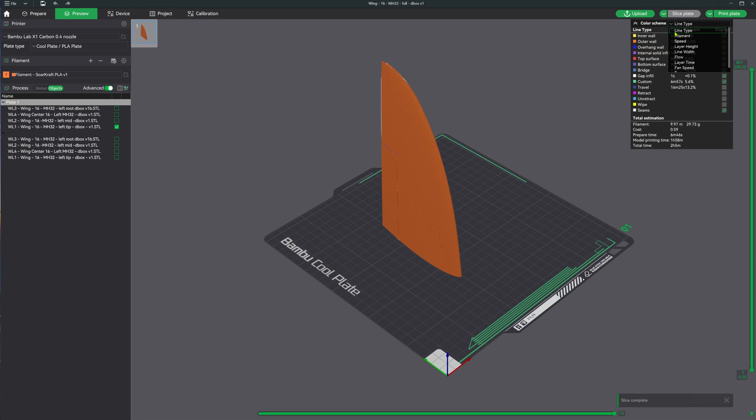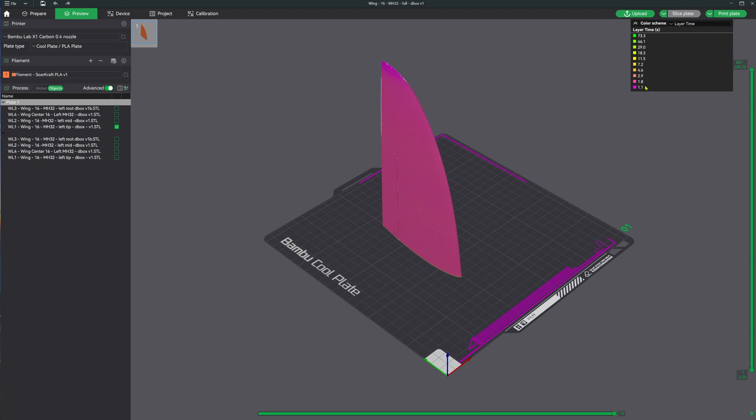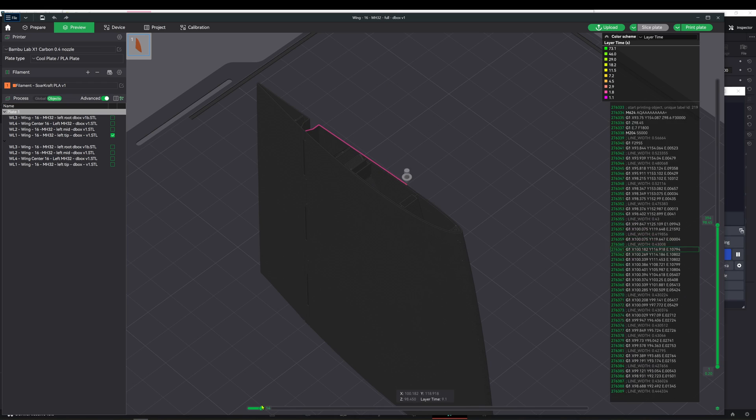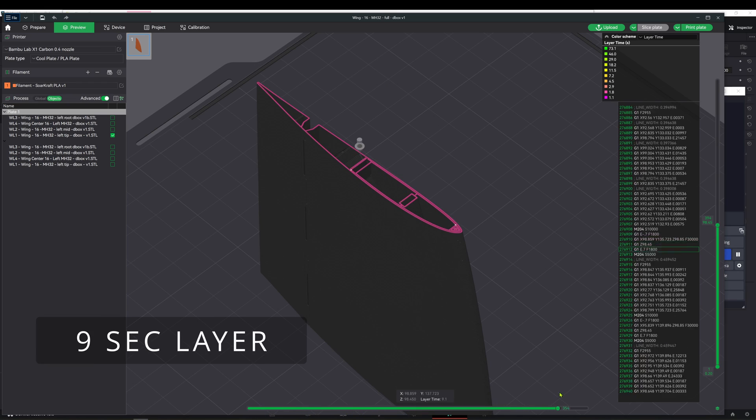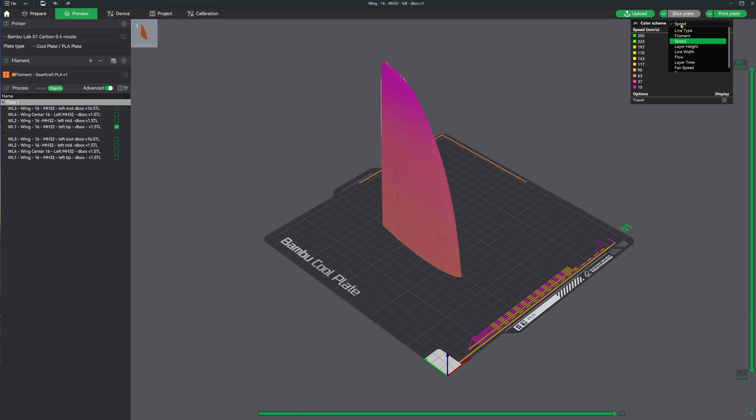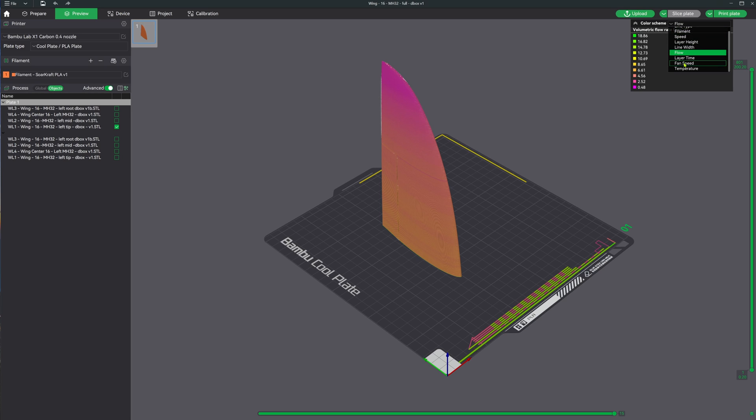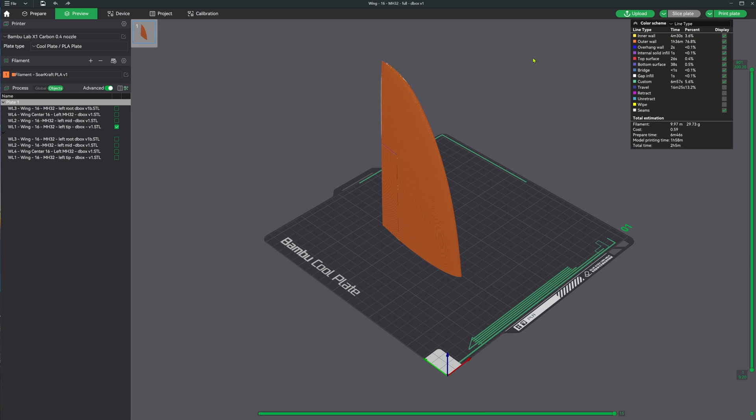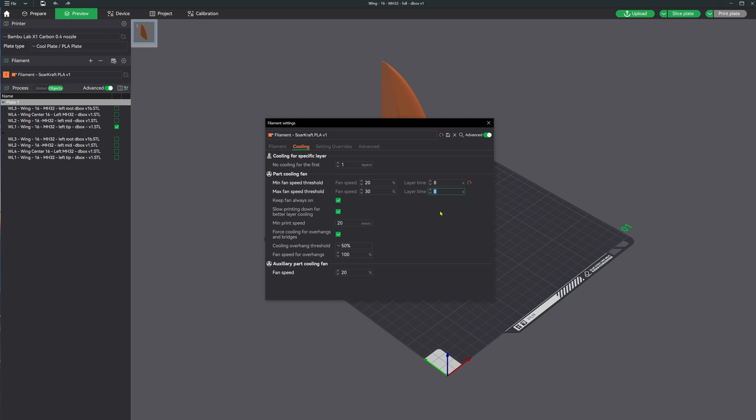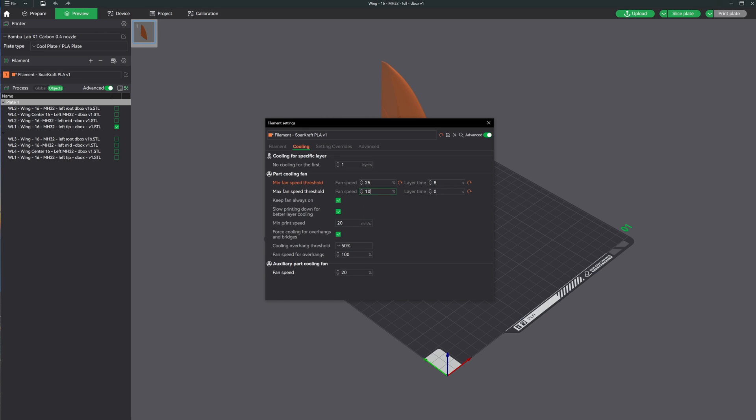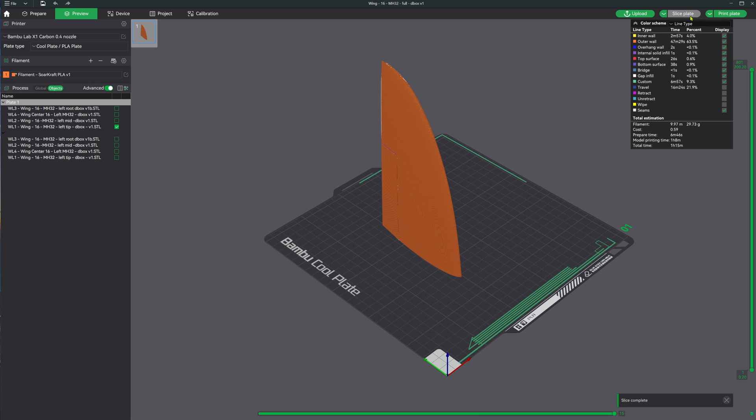Another place to look to save print time is the carryover of the minimum layer time. This was to keep from overheating quick layers, and since there is little or no infill in these parts, most layer print times are very short when only printing one part, especially wing tips, and you easily hit the threshold to slow things down. Reduced fan was also used on parts to help with layer adhesion and slow cooling to reduce brittleness. Well, with this faster printing and specific material tuning, we can turn up the fan speed and turn off this minimum layer time and keep the printer running at top speed.